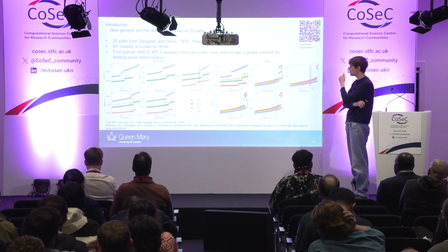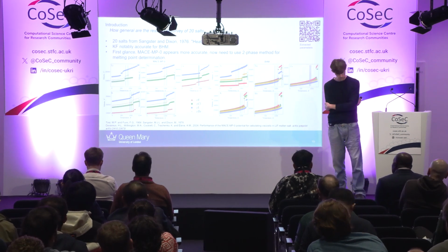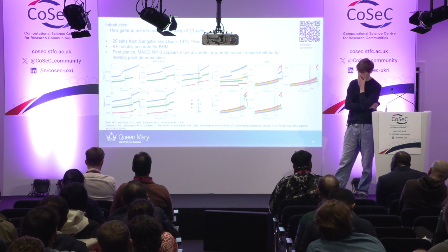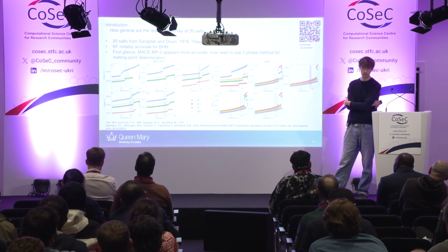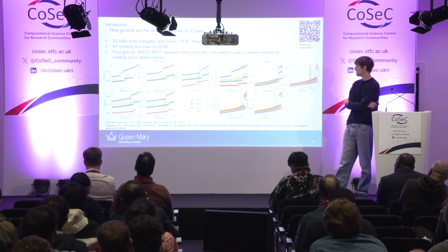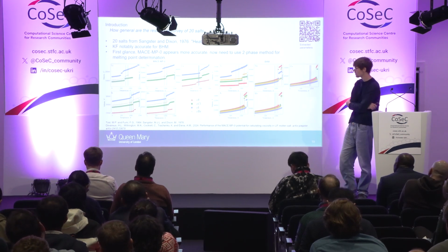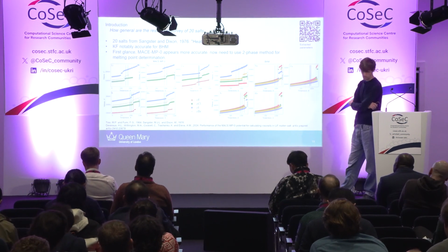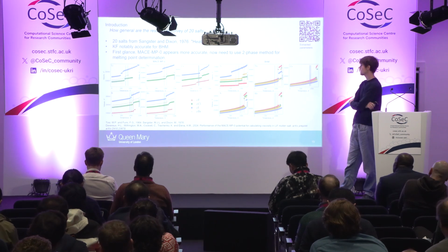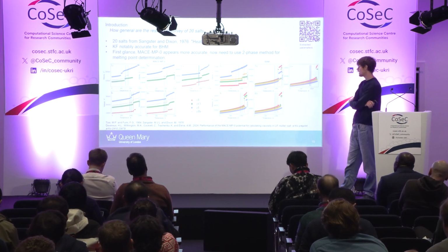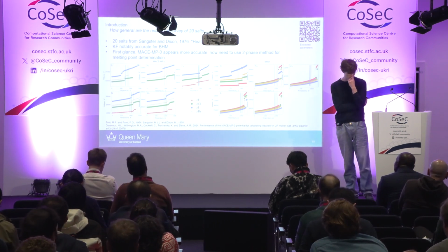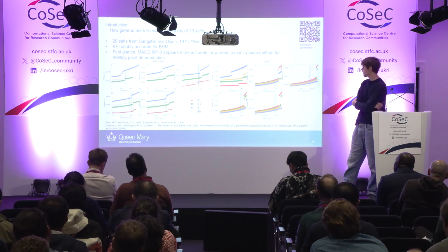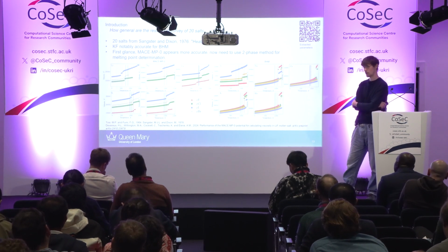So what we can do is, at least for the empirical models, we can extract the parameters from the Fumi and Tosi rules, which have been used for a long time, and simulate those in the same methodology, and do the same also in MACE, just by swapping over the configurations and the atoms, so that the potential can model those. And what we find is, generally, the instability occurs at a much different temperature in the empirical models, and it's generally slightly more accurate in the MACE models.